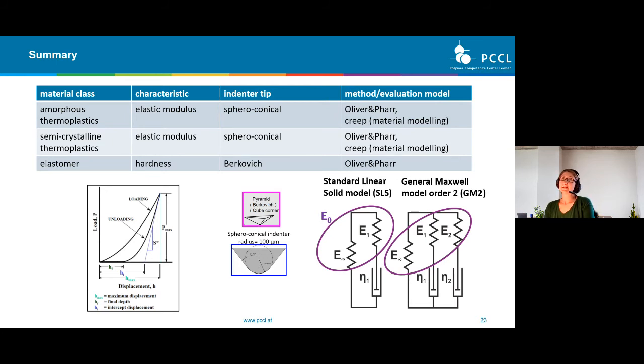If we investigate a semi-crystalline thermoplastic and we want to get the elastic modulus, we should also use a large spheroconical indenter tip. As a method, the Oliver and Pharr method is also good enough. But we could also use a creep measurement in combination with a more sophisticated material modeling.